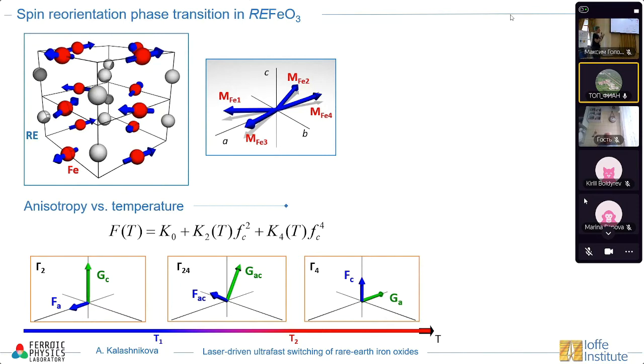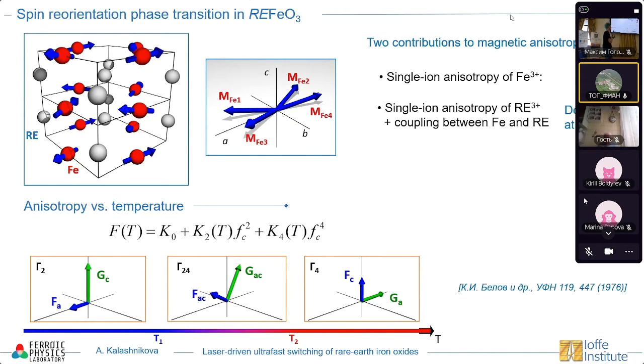In principle, this kind of transition is not possible to describe in terms of just single ion anisotropy, and it was very intensively investigated in the 70s and 80s of the last century. It was suggested that in principle there is a competition between two contributions to magnetic anisotropy. One comes from the single ion anisotropy of iron ions, and this is the anisotropy which stabilizes this gamma 4 phase. But at low temperatures, another contribution starts to play a role and starts to dominate, and this is basically a single ion anisotropy of rare earth ions and their coupling to the iron sublattice.